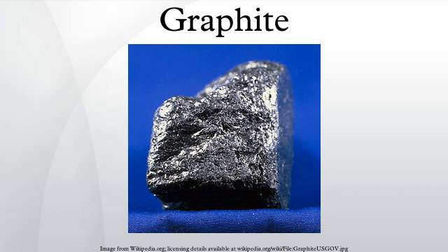A high-quality flake graphite product that closely resembles natural flake graphite can be made from steelmaking kish. Kish is a large volume near molten waste skimmed from the molten iron feed to a basic oxygen furnace, and consists of a mix of graphite, lime-rich slag, and some iron. The iron is recycled on-site, leaving a mixture of graphite and slag. The best recovery process uses hydraulic classification to get a 70% graphite rough concentrate. Leaching this concentrate with hydrochloric acid gives a 95% graphite product with a flake size ranging from 10 mesh down.